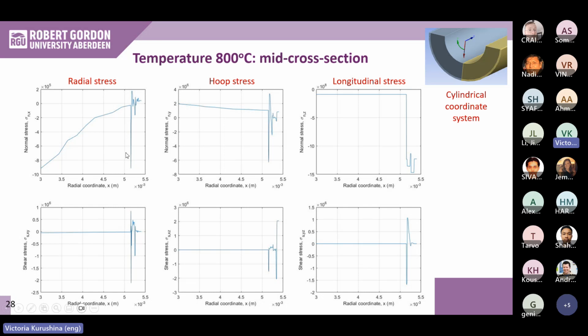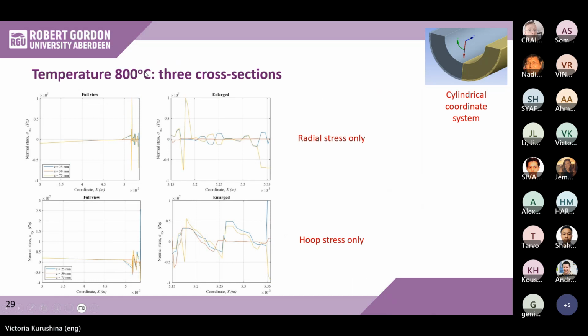So you can see that these stresses start fluctuating largely, and the amplitude of these fluctuations is sometimes an order of magnitude higher than the stresses exhibited anywhere inside the substrate. So this is a combination of the different material thickness and the frictionless contacts that we incorporate into the model.